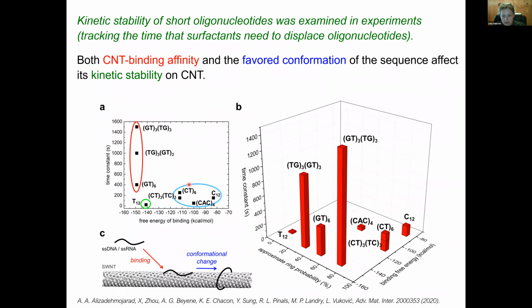The experimentalists also checked, we screened, whether this favored conformation of the DNAs is going to be affecting or have some correlation with the kinetic stability of these DNAs on nanotubes. That's what the experimentalists measured, the kinetic stability of these DNAs on the nanotubes. And we found basically that kinetic stability depends on the conformation and also on the carbon nanotube binding affinity, which we showed correlations for together with them. But our work was basically screening all these sequences computationally.